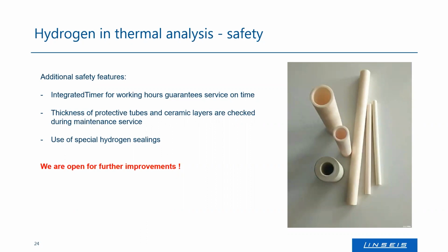And during the maintenance, the inner tubings, sealings, and fittings are checked, thickness is measured, and surfaces are controlled to make sure that there's no little crack, no risk of breaking during operation, and so on. And of course, we use special hydrogen sealings that should be replaced during maintenance as well. And as said, there is an integrated timer that monitors the working temperatures and hours and gives you a hint when maintenance is necessary. And doing this, we are able to operate all our systems in hydrogen atmosphere.